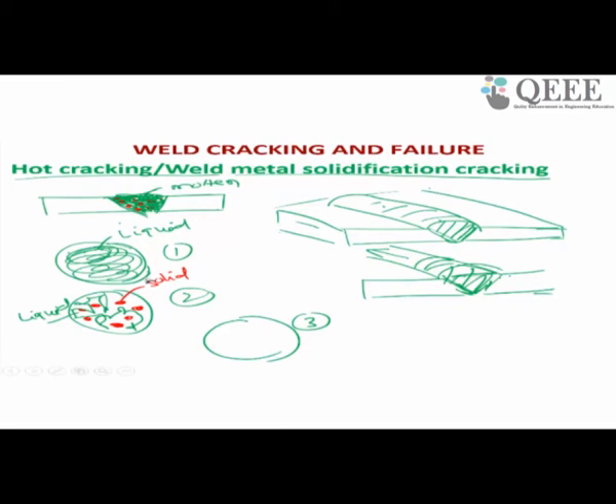Now suppose your material has iron, sulfur and phosphorus. The melting point of iron is around 1538 degrees centigrade. Similarly, the melting points of sulfur and phosphorus are very low, much less than 1000 degrees centigrade, much lower than the melting point of iron. So in your weld pool, in your alloy base material, all three are there.